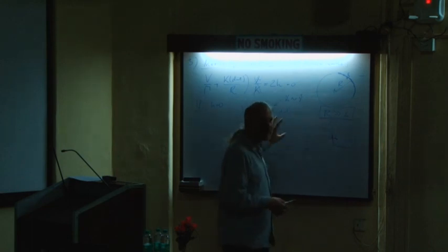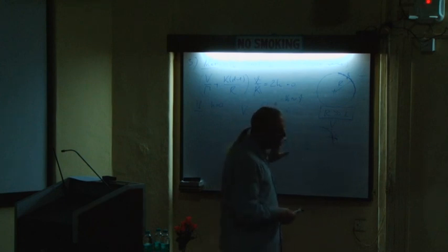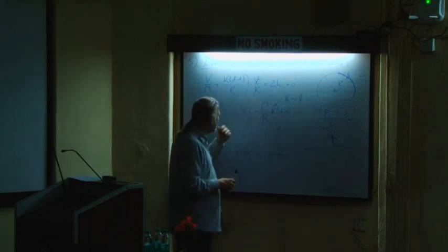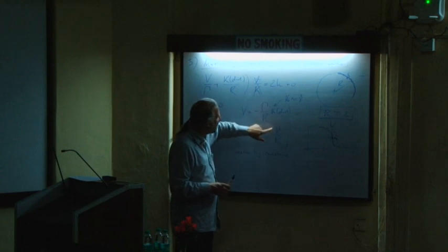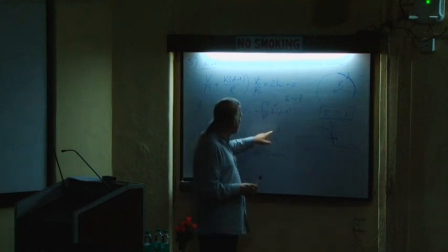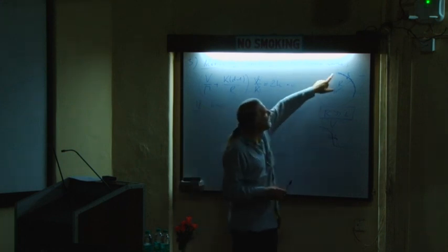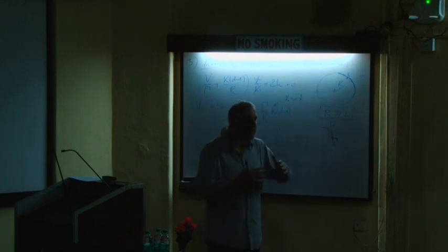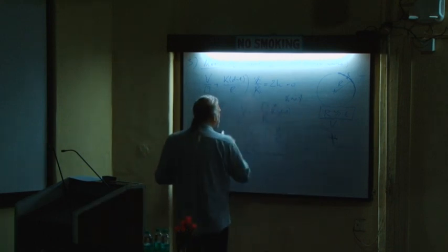Okay? So here I have done it for you for magnetic domains, but this phenomenon is perfectly general. If you have two phases of the same energy, and if the interface can move freely, then it will move by curvature. It will satisfy this relation. And the important thing, the driving force here is the surface tension, the surface free energy times the curvature. Because the surface free energy tells you the energy cost of the interface, and the curvature tells you in some sense by how much you can reduce the surface when you move inward. Okay, so this is perfectly general.